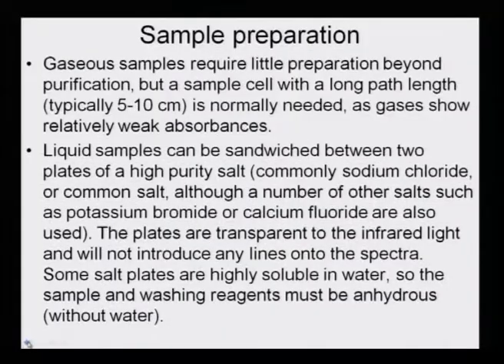Liquid samples can be sandwiched between two plates of high purity salt, commonly sodium chloride or common salt, although a number of other salts such as potassium bromide and calcium fluoride are also used. The plates are transparent to the infrared light and will not introduce any lines onto the spectra. Some salt plates are highly soluble in water. So, the sample and washing reagents must be anhydrous, without water.